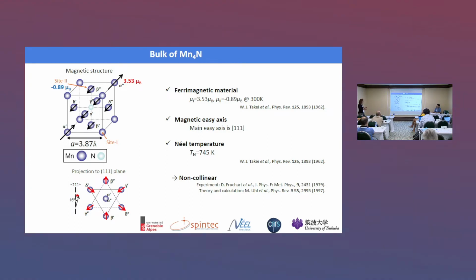In the bulk, manganese nitride is a ferrimagnetic material with two sublattices: manganese 1 in the corner site, with a large moment, and manganese 2 in the face-centered site. The easy magnetic axis is in the 111 direction. It has a pretty high Néel temperature, and in the bulk it is a non-collinear ferrimagnet.